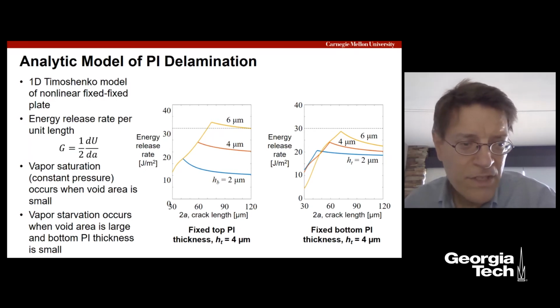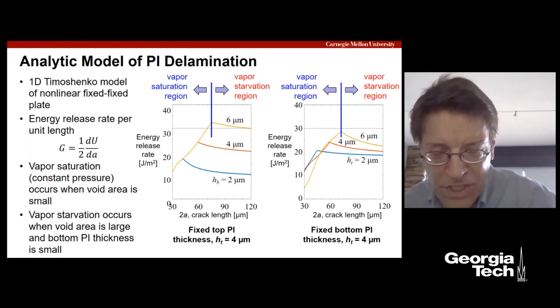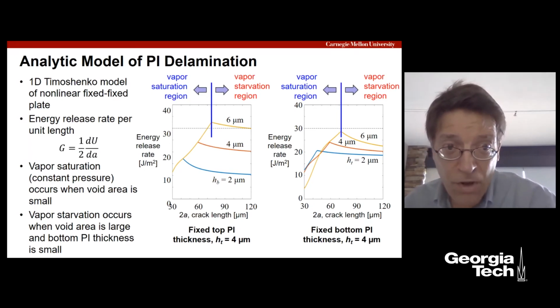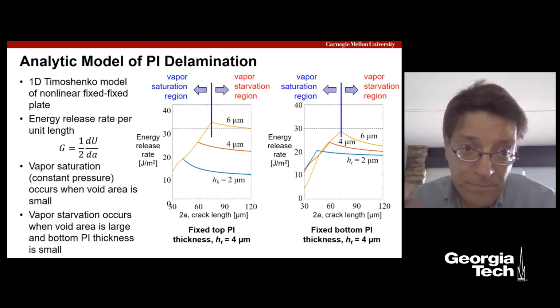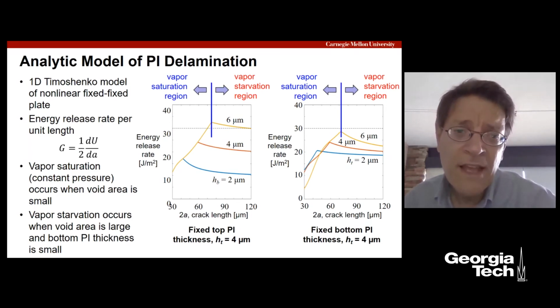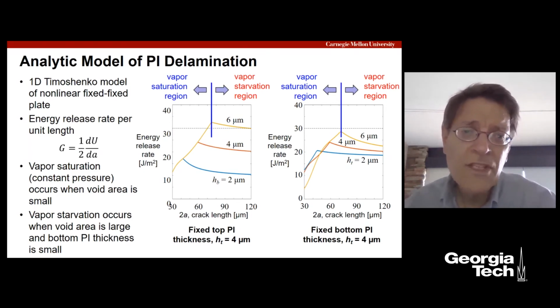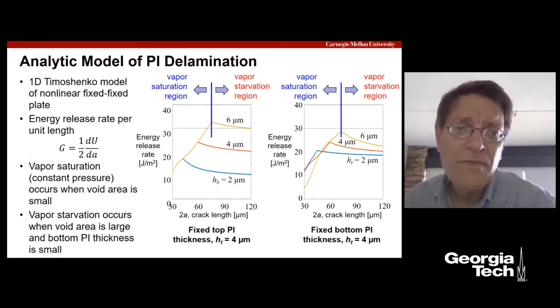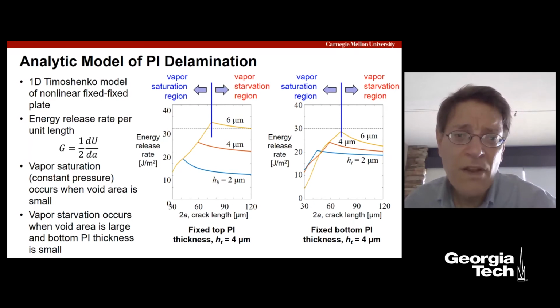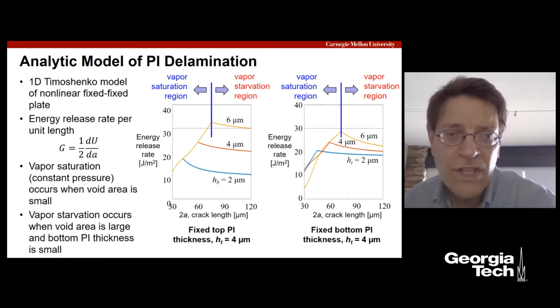What else is interesting about this is there are these two regions that you see distinctly in the model. One is at small crack length, where there isn't much volume, but there's an ample amount of liquid, so the water gets into that volume and it saturates and creates a pressure from the vapor saturation. That's not dependent at all on the bottom layer thickness, because there's plenty of water. But then we hit the so-called vapor starvation region, where the crack becomes large enough that you now have a large void. There isn't as much vapor to feed that volume, and all of a sudden the energy release rate plateaus and starts to go down.